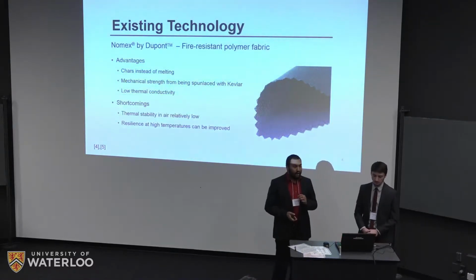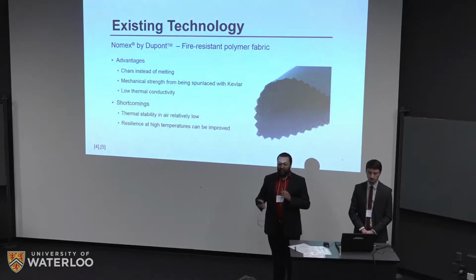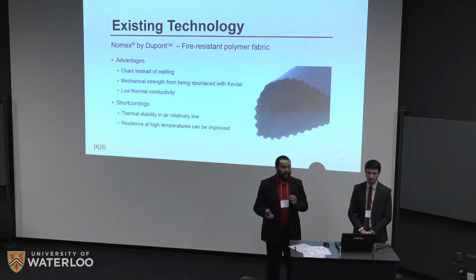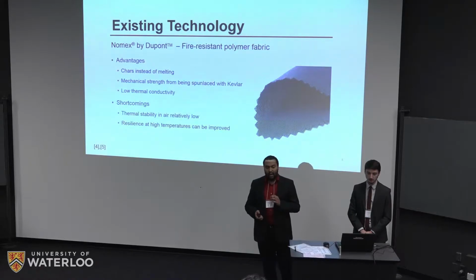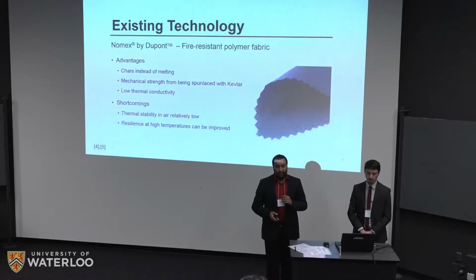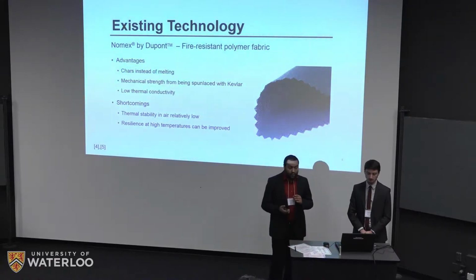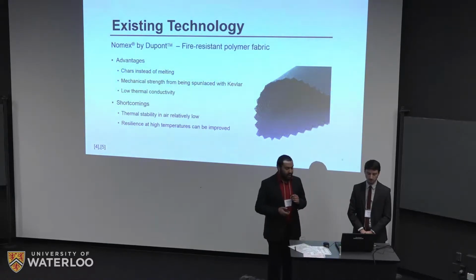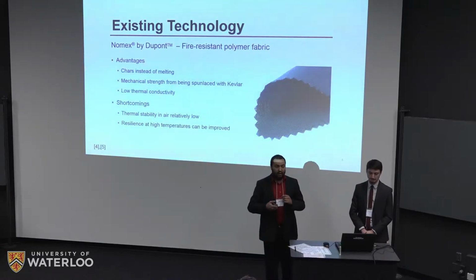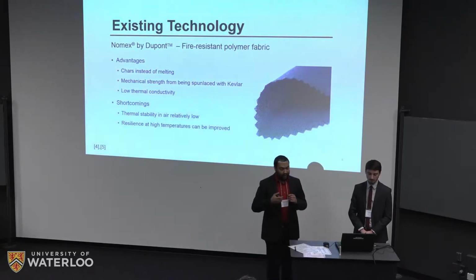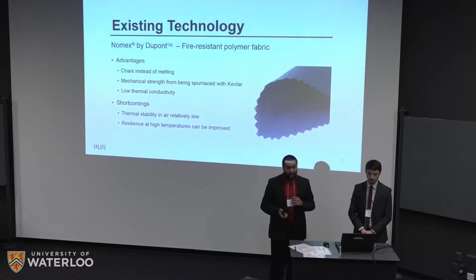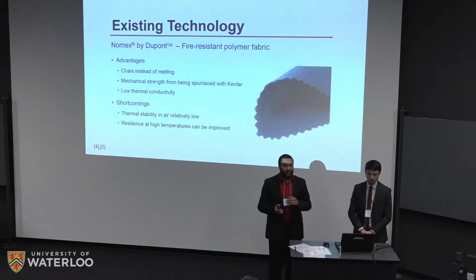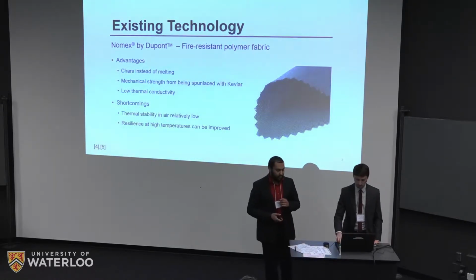So some of the existing technology, the main one is Nomex by DuPont. This is a fire-resistant polymer fabric. A couple of the main advantages of this fabric, it chars instead of melting, and it doesn't catch fire. And it also has low thermal conductivity, so the heat dissipation through the fabric isn't very high. However, a couple of the shortcomings that we wanted to focus on, thermal stability in air is relatively low. We'll talk about this a little bit further on. And the resilience at high temperatures we think can be significantly improved.